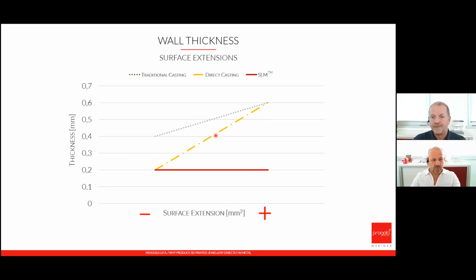The chart shows how necessary wall thickness increases for traditional and direct casting, okay, and this is the movement when the surface to be obtained increases, okay. SLM instead, that is the red line, can maintain the same wall thickness regardless of the surface extension. You can see also that for traditional casting, however, the starting point for wall thickness is already higher with respect to the other due to the limits of rubber injection and wax extraction.